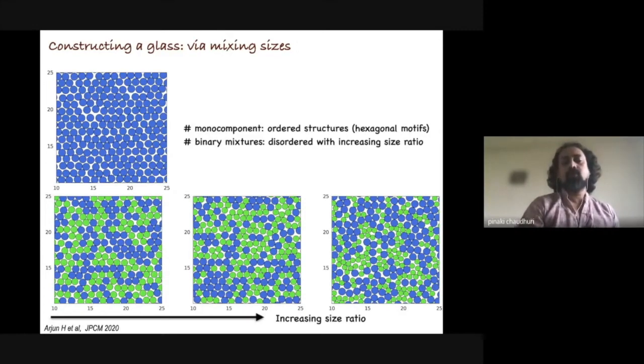So if you go in the lower panel from left to right, we increase the size ratio of this mixture. So you have large particles and small particles, and beyond this certain threshold size ratio, you no longer see these hexagonal motifs, that is, the order has been broken, but still you can have rigidity inside the system.